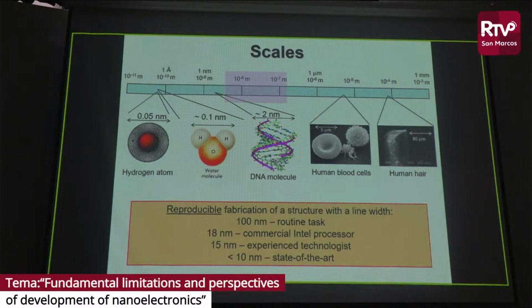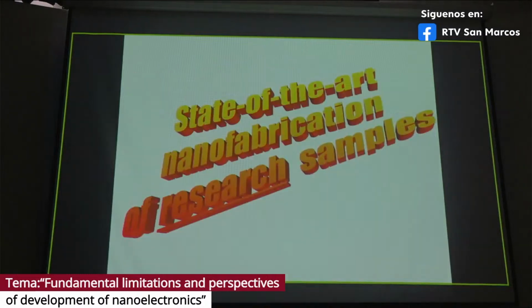What about nanotechnology? Nowadays 100 nanometers is already a routine task for electron lithography. 18 nanometers is already commercial, I mean strictly commercial Intel processors, not just a PR announcement. At 15 nanometers, you need to be quite an experienced technologist and have good equipment. And everything below 10 nanometers can be considered state of the art. So I will speak about how in our lab we developed a method to fabricate sub-10 nanometer structures, and not only to fabricate, but to be capable of reducing the size without damaging the structure.